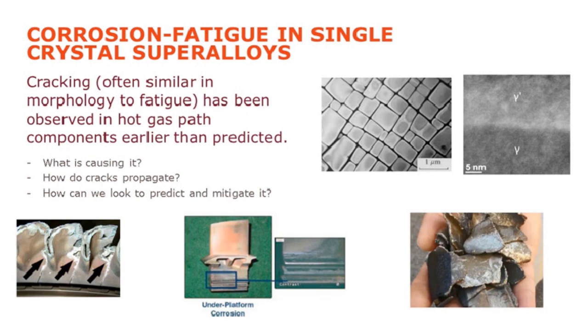The image on the bottom left is of an industrial gas turbine, and we can see corrosion damage on the platform where the arrows are pointing, and actually bits of material have broken off there. The middle image is under corrosion platform, and again this is quite typical of what we would see. It's a highly stressed area of the blade, but at lower temperatures than some other parts of the blade. But we see colonies of cracks propagating through the platform, through the root region, that highly stressed region there.